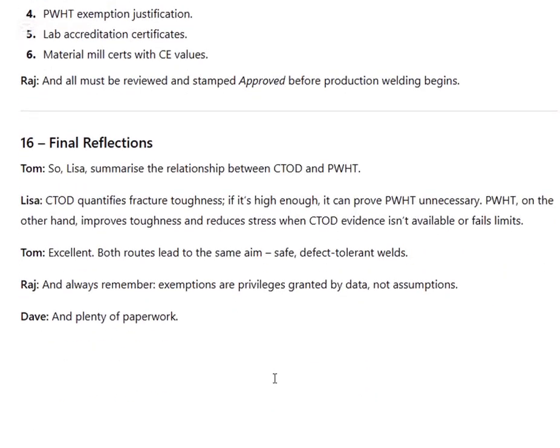Documentation package, final reflection, key takeaways. Number of specimens as per BS greater than 3. Temperature 0 degrees Celsius plus minus 2. Minimum delta 0.2 or greater. Base metal 0.35. CE for steel less than or equal to max CE. And PWHT for thickness less than 20, thickness greater than 40, and all other parts greater than 50. PWHT omission: written consent only, approval based on CTOD, FMA, fracture mechanics assessment language.